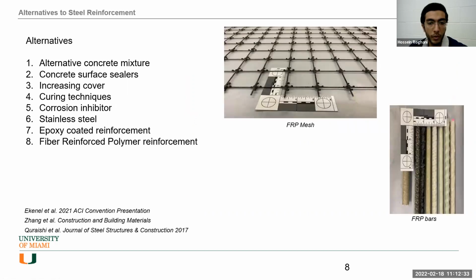So as I discussed before, we have many different alternatives for the steel to prevent the corrosion. You can use a different concrete mixture. You can have concrete surface sealers. You can increase your cover. You can use better curing techniques, corrosion inhibitors, stainless steel, epoxy coated, and at the end, last but not least, the fiber reinforced polymer reinforcement, which is our main interest here.